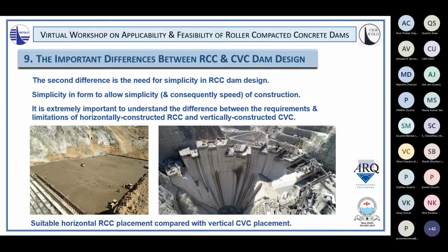It's extremely important to understand the difference between the requirements and limitations of horizontally constructed RCC and vertically constructed conventional mass concrete. And these two figures illustrate this significant difference. In the case of RCC on the left, what you need is a large open area to allow very simple, very rapid transportation, dumping, spreading, and compaction, or horizontal compaction of your RCC layers. Anything that goes inside that will cause an interference.